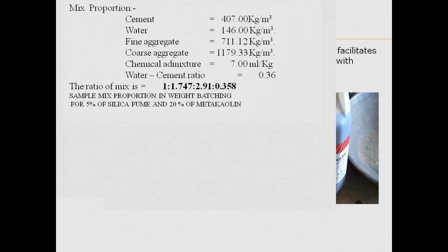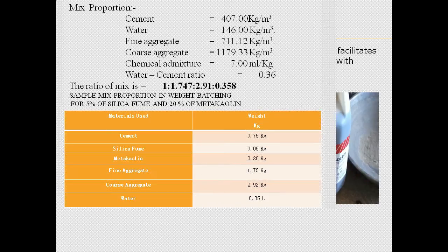From all these, we have got the mix proportion as 1 : 1.747 : 2.91 : 0.358. Then the table represents the weight batching for 5% of silica fume and 20% of metakaolin. Then we have got the compressive strength, and as you can see, for 0% silica fume and 0% metakaolin, we have got the 7 days, 14 days and 28 days strength, which was found to be 44.62.